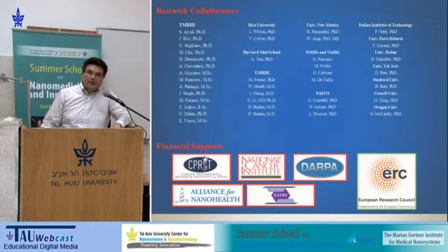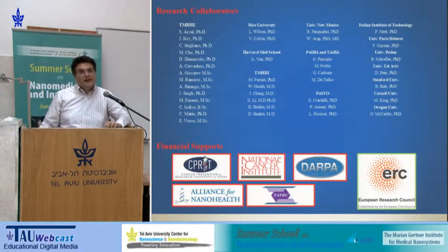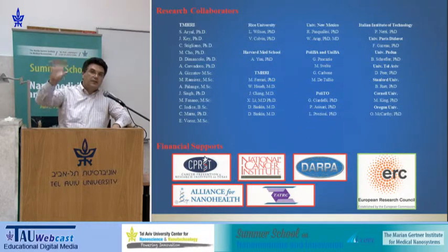Especially for the discoidal polymeric nanoconstructs, within the first 2 hours of imaging with PET, we see a lot of signal coming from the lungs, and the particles are staying for that time within the microvasculature of the lungs. But because of their deformability, they come out, so they're not staying there. But this is also something that we are using, for instance, for targeting lung cancer. Because in lung cancer, on the other hand, you will have hydrodynamic conditions that reduce the hemodynamic forces, and these larger particles will be able to accumulate. With lung cancer, as well as melanoma metastasis into the lungs, we do see significant accumulation. These are other studies that we are developing with PET imaging, showing clearly after a few hours that the lungs have been washed, but you see these mets and the primary tumor that is actually highlighted.